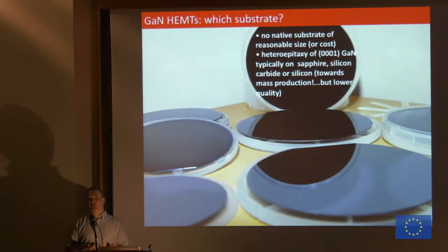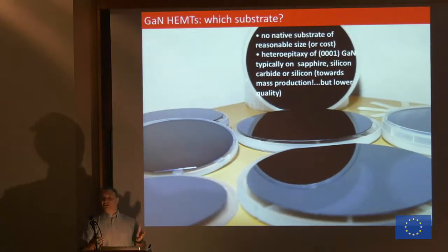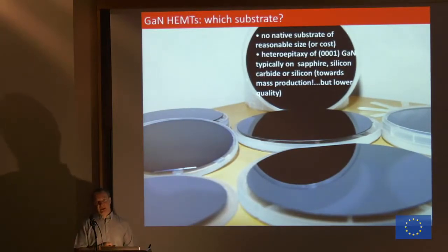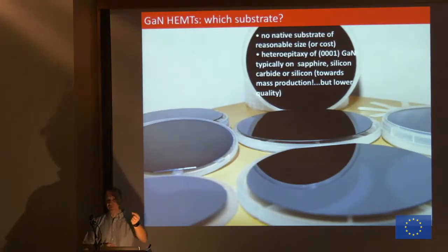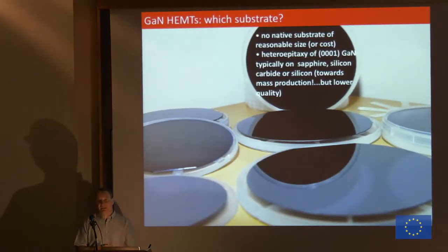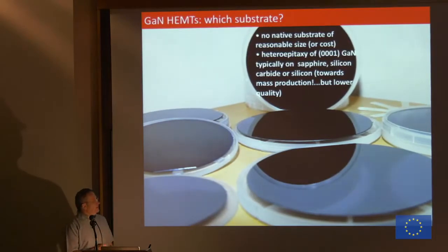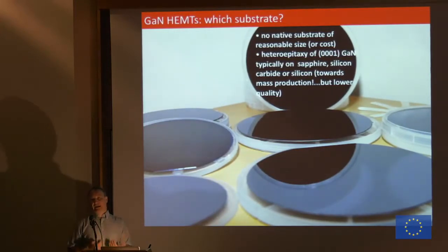So the question is, why don't we have GaN on GaN? Freestanding gallium nitride substrate is not available today in a decent size. So we cannot grow classically, like 6-inch, 8-inch, or 12-inch silicon, or like 6-inch silicon carbide. We cannot grow an ingot that we can cut to make a wafer like this. For gallium nitride, the maximum that we can do is a few millimeters by a few millimeters, or maybe a centimeter if you're lucky. So you cannot do anything of real industrial size with this. So we cannot have GaN on GaN.